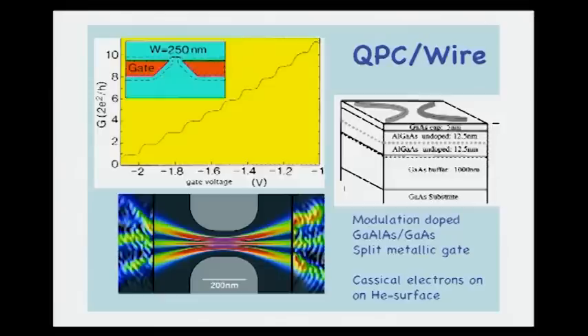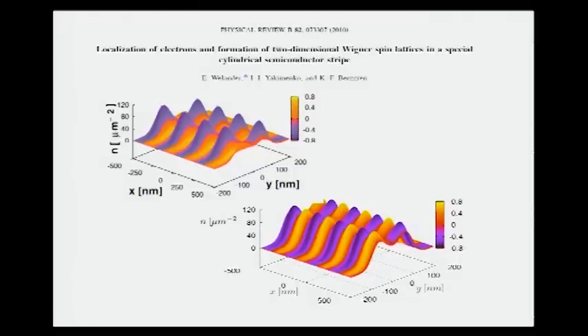And I should end here by showing a graph which I'm sort of pleased with. This is the spin-polarized DFT calculation of the electron gas in a wire, a circular wire, sorry, cylindrical wire. And you can see here the spin-up density, these blue sides. So evidently you form some kind of zigzag lattice when electron density becomes very small. And in the same way, you also get a spin-down lattice, which is not shown here, but it would be the same, shifted in phase. And when you put them together, you form a very clear lattice, which would be an antiferromagnetic Wigner lattice in a 2D electron gas at the interface of a semiconductor device.